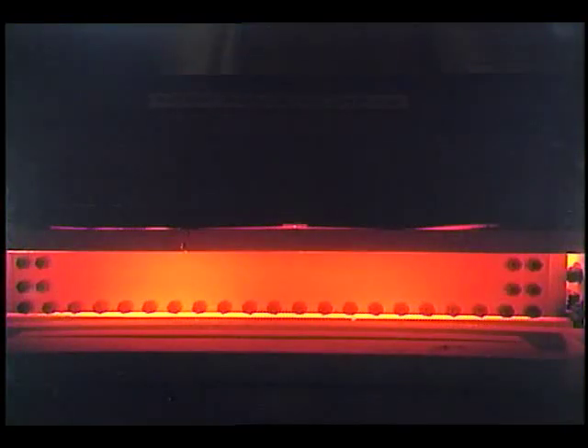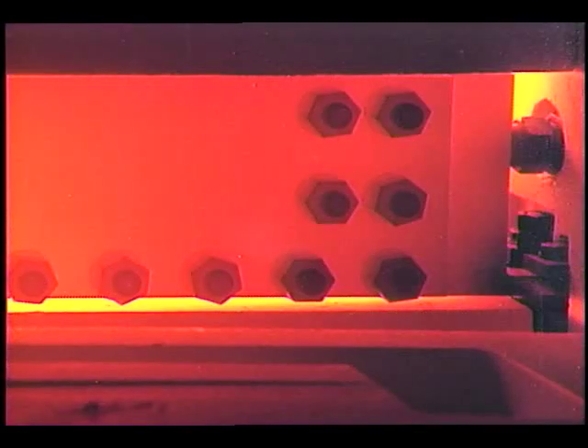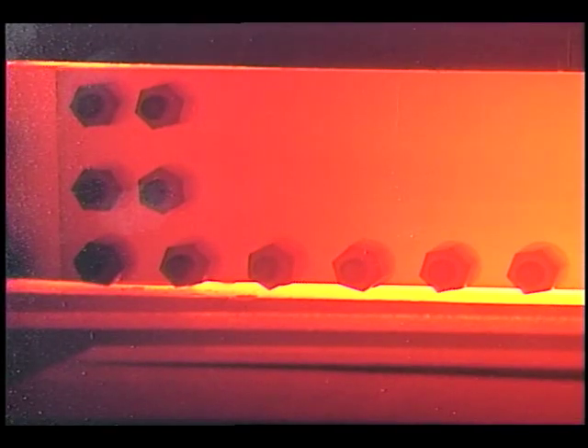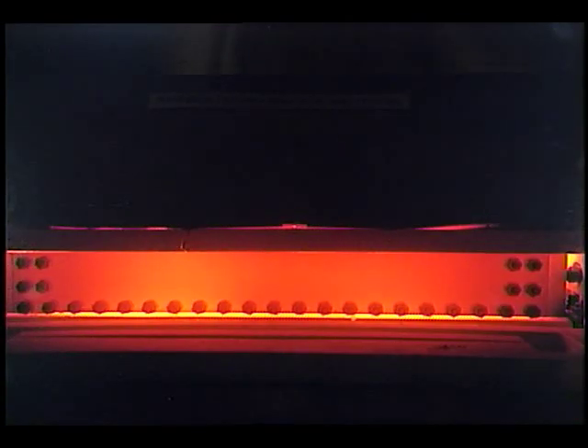The hot performance of the two seals was measured at NASA Lewis using a specially designed test fixture. Though one cannot see the seals in this picture, the seals are mounted behind the front wall of the hot test rig. Tests have shown that the ceramic wafer seal has very low leakage, even at temperatures exceeding 1400 degrees Fahrenheit. It seals both flat and distorted walls equally well.